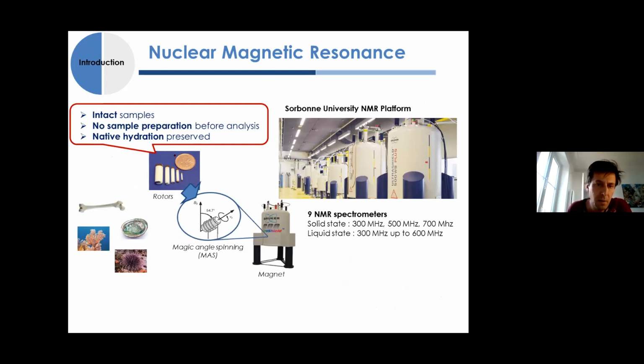And as I said before, that's pretty interesting because you don't need sample preparation. Here you have a picture of the sample holder that we are using, called rotors. The diameter is about 7 millimeters, and the height is about 1 centimeter for that rotor, for instance. So it depends on the rotor, of course, but you are dealing with masses ranging about hundreds of milligrams.